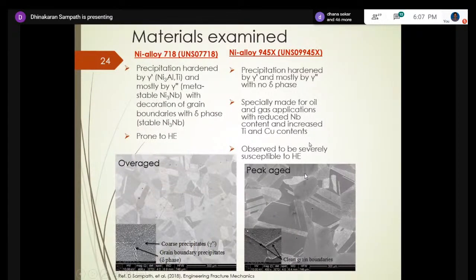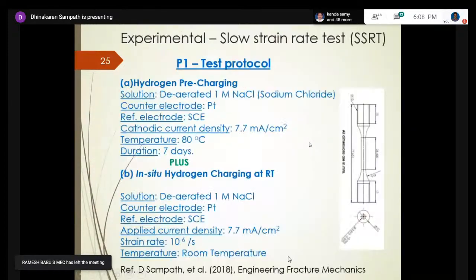So peak aged is one particular size of the precipitate at which the material attains its highest strength. So this is a peak aged microstructure. You can see that it has big grains and no grain boundary precipitates, which is made for oil and gas. And then the experiment I'm showing here. So what we did was we used this cylindrical specimen based on a NACE standard. That's the standard for conducting slow strain rate tests.